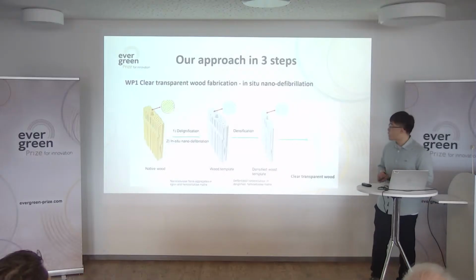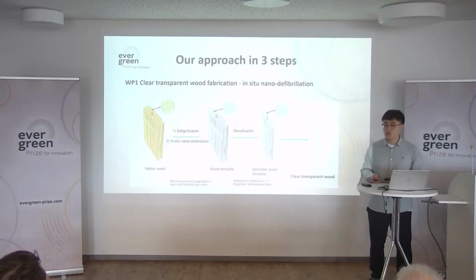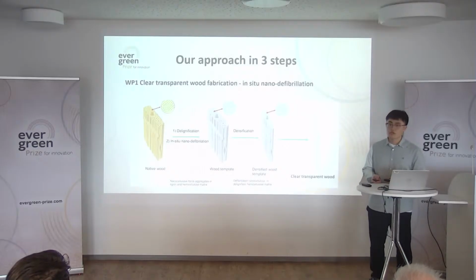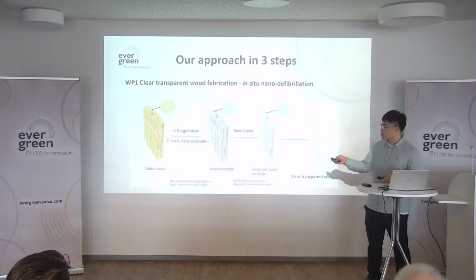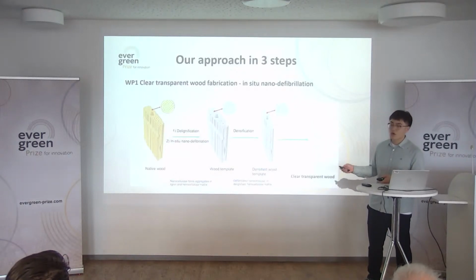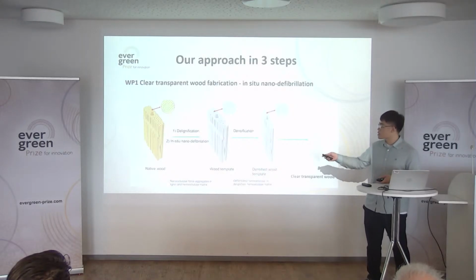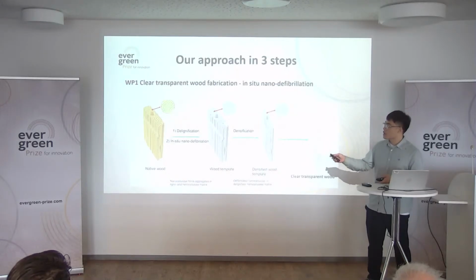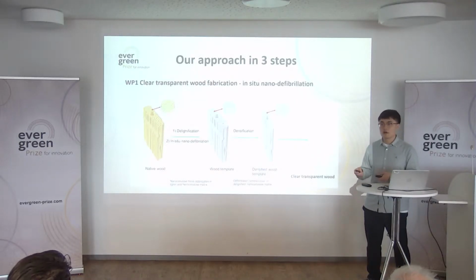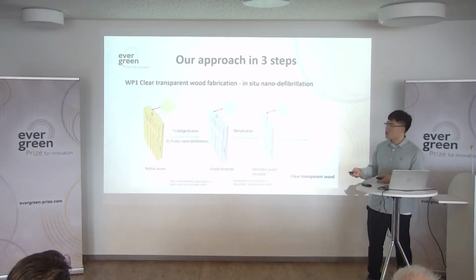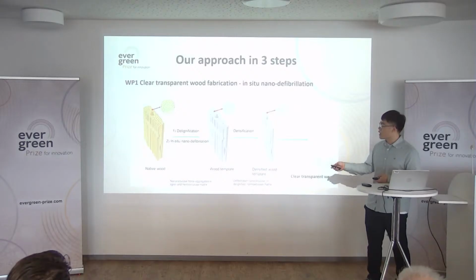Thanks for the introduction of the background from Yuan. Next I will introduce the detailed approaches to fabricate the transparent wood-based luminescent solar concentrator. We plan to solve the issues in steps. The first step is to fabricate a clear transparent wood with low haze. Normally we produce a transparent wood just with delignification, and after that we do the polymer infiltration. But here we add a step, in situ nano-defibrillation. It is used to reduce the aggregation of the nanocellulose inside the cell wall, and it can assist the polymer infiltration and give a more homogeneous wood-based material. This can help us reduce optical heterogeneity and the interface debonding, the problems that we mentioned before. And after that, densification is also added to improve the wood content inside the structure.